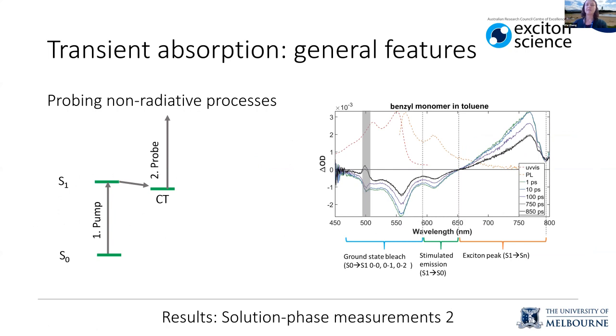So what we use is transient absorption, and I thought I would just give some general features so that you'll be on board for the rest of the talk. So here we have the transient absorption spectra of one of the monomers in toluene, so in a not very high dielectric solvent. And here I've put the absorption spectrum and the emission spectrum over the top, so you can see what they relate to in the transient absorption. So first you have what's called the ground state bleach, which should mirror the absorption spectrum. So that's just saying that you're depopulating your ground state.